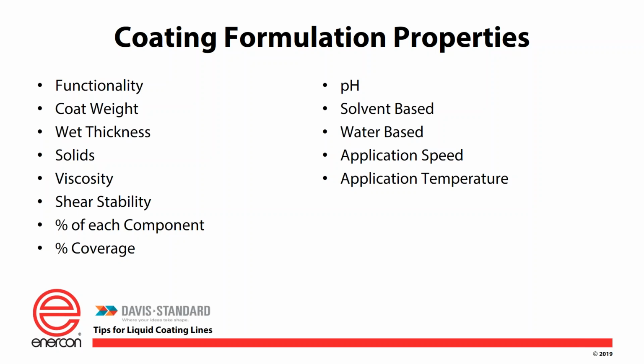Water-based, again, if we're going to use water-based, it's much easier to handle, but sometimes harder to dry. Dryers might be longer. Evaporation rates on solvents versus waters are different, so we need to identify these. Also, if you're running both on the same machine, in a dryer process, we use LFL detectors, which is lower flammable limits. And if you're only doing solvents, you could buy a certain brand. However, if you're going to put water through the same dryer, you need to buy a more advanced version of that, which is a little more expensive. If you don't do this, then you could actually damage your LFL sensors.